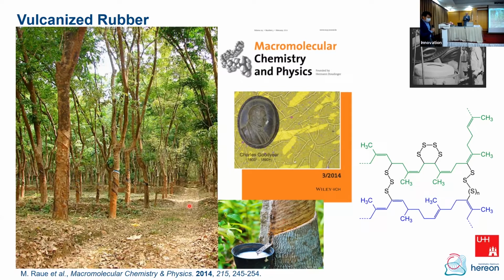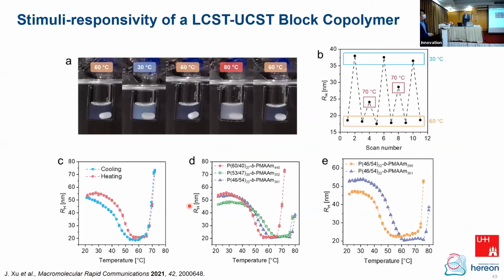And when you talk about the combination of the LCST and UCST, so that we have the window of solubility, I'm not sure I catch all information from the slide, but how small is the range that you achieved? From what temperature to what temperature is it soluble? It was around 10 degrees as a gap, so far. But again, this you can adjust. The co-monomers we use for the LCST block are just the set we use. We could also use co-monomers which would lead to a lower LCST, and by that maybe bring the LCST further down.